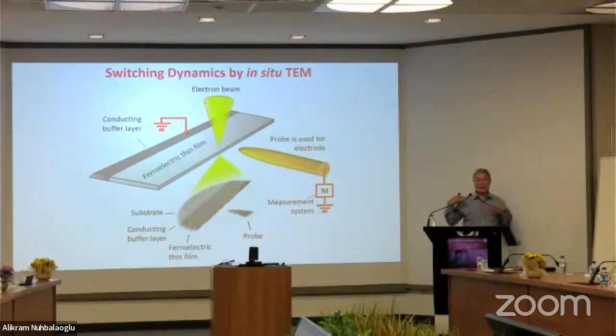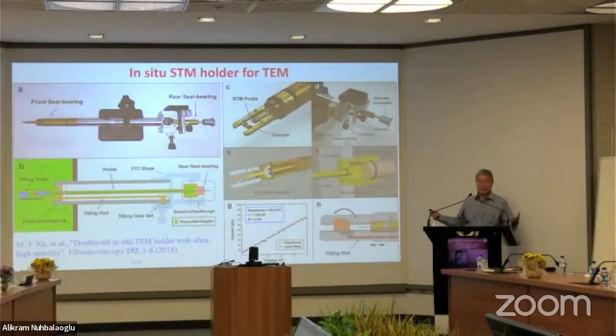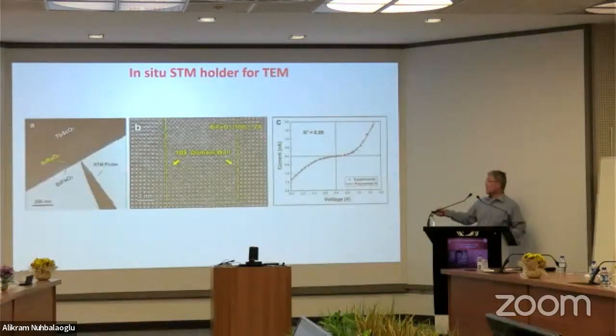All right. So I kept this in mind when I became a professor at Michigan and still wanted to solve this problem. And then one of the graduate students was committed, Chris Nelson. We started with a conventional prototype, the scanning probe in the TEM, with a bias. And then the system looked good and promising, but it's really not designed for this type of work. So we developed the technique and brought a lot of components we designed. We made a new product, which has become very stable, and this new product allows you to apply bias to the point of interest. And then you can see atomic scale action.